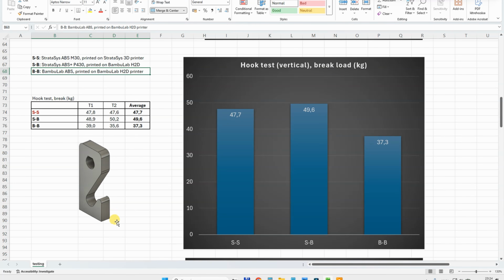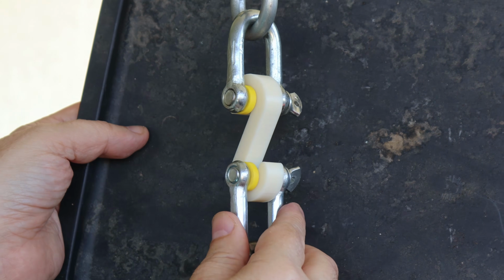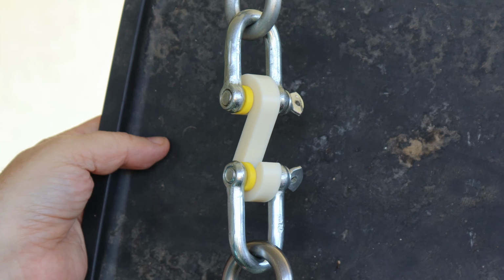And this hook is printed in vertical position, and it must resist the bending and tensile strength. Now the tensile strength is along the z-axis, so it is actually the layer adhesion, and we can see the Bambu Lab is weakest in this case, and the two Stratasys ABS are the strongest, but still a small advantage with the P430. And now the S hook, which is printed in horizontal position.